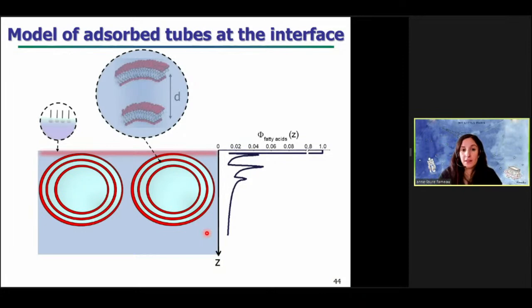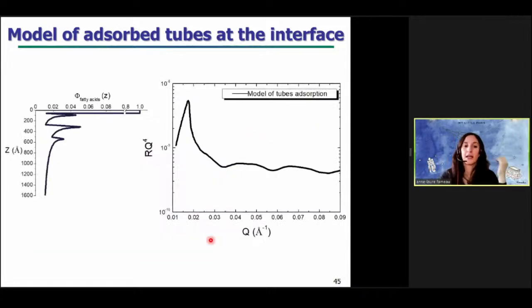So we developed a mathematical model of tubes adsorbed at the interface below a fatty acid monolayer. And in this mathematical model, we took tubes with exactly the same dimensions that we determined previously in bulk by microscopy and scattering experiments. And the main parameters in our model are the interlayer spacing and the number of tubes adsorbed at the interface. From this model, we calculated the corresponding profile of the fatty acid fraction according to the distance to the surface. Again, from this profile, we calculated the corresponding reflectivity curve that you can see here in black.